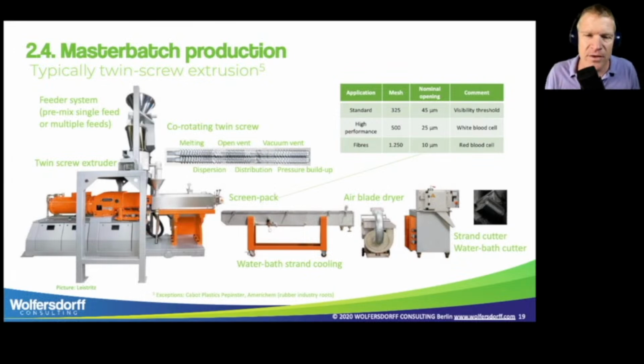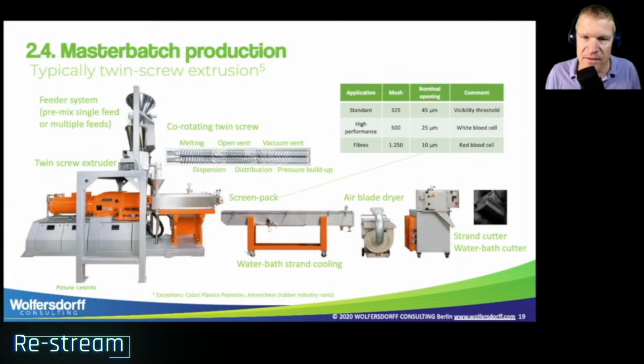The screw, as you can see in the middle of the slide, has different sections. The first section is for melting the polymer. Then for dispersing the polymer with all the ingredients, there might be vents, there might be open vents. At the end of the extrusion, there might be a vacuum vent to take out the volatiles. So after the dispersion units, there could be distribution screw elements. And at the end of the screw, we need to build up the pressure for the extrusion.